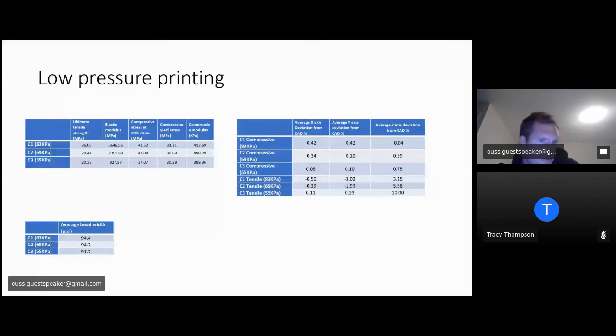So I managed to 3D print at normal pressure, ambient pressure, and then slowly reduce the pressure down to 55 kPa. And that's a really important figure, because 55 kPa is the expected pressure that will be the lowest possible pressure that will be used for human exploration on Lunar Gateway. So that's obviously really important, because if you're going to 3D print parts on Lunar Gateway, then you need to know if the drop in pressure is going to affect anything. So I gave it a go. And what I saw with this is very interesting.